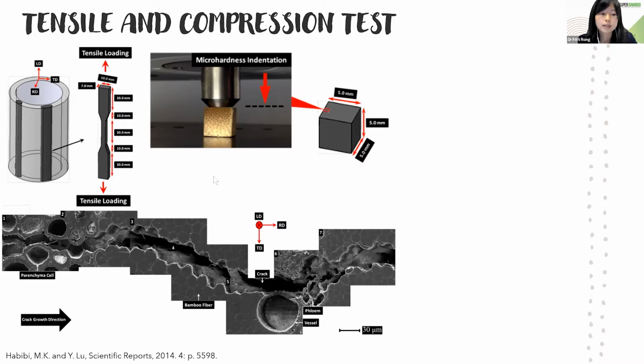Once the initial crack reaches the critical conditions for further crack growth, it will propagate along the parenchyma cell boundaries. We can see here, this is the parenchyma cell. It will usually crack along the boundaries until it reaches the fibers. But we can see it will also crack through the interface of the bamboo fiber, like here, until it reaches the vessels, because a vessel is more like a hollow. So the material will be stopped here and then find another way to crack.